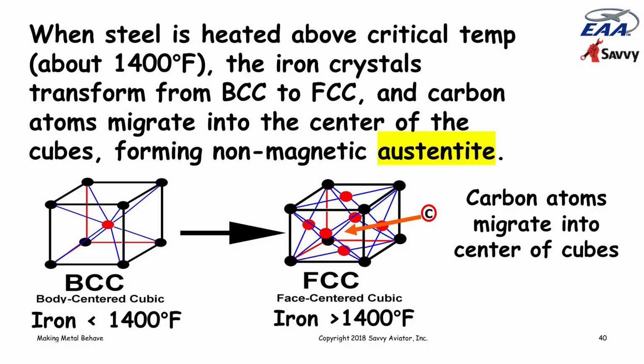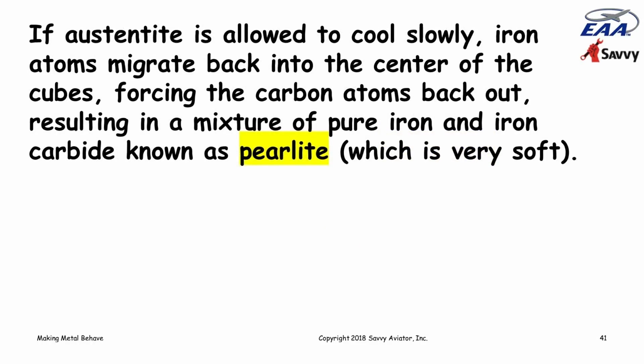Now, if the austenite is allowed to cool slowly, then the iron atoms migrate back into the center of the cubes, and the carbon atoms come back out of the center of the cubes, and the result is a mixture of pure iron, called alpha iron, and a compound of iron called iron carbide. And that mixture is a very soft, very ductile material called pearlite.